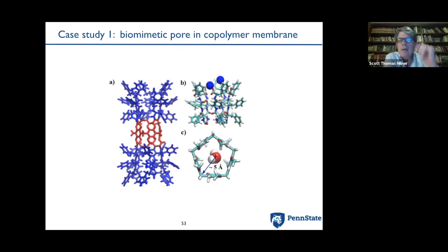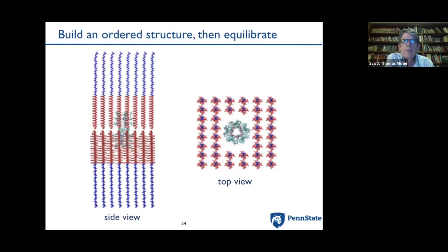And it's just about big enough to pass a water molecule, and these have been synthesized and studied, embedded not in lipid membranes, but in membranes made from diblock copolymers, where the blue polymer, as the color implies, is hydrophilic. It's polyethylene oxide of a short oligomer, and the red portion is hydrophobic, a hydrocarbon.